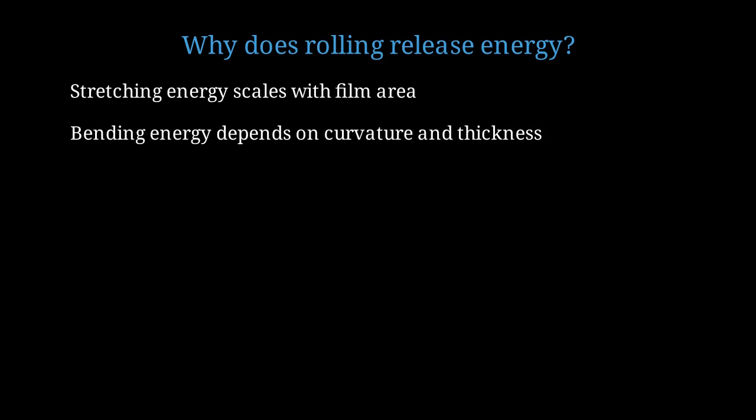The key is that bending energy scales as h cubed, while stretching energy scales as h. The stretching energy is 1/2 E epsilon squared times L squared times h. Notice it's linear in thickness h. The bending energy is 1/2 E kappa squared times h cubed over 12 times L squared. Notice it's cubic in thickness h.